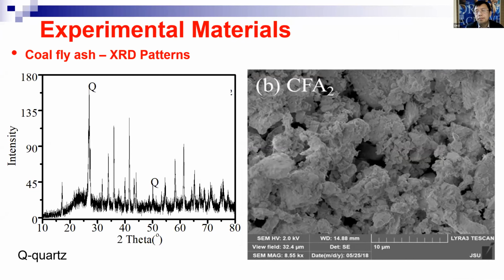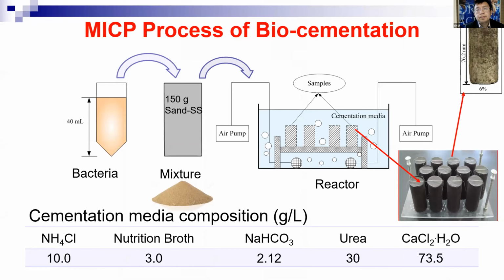The reason is, as we mentioned, this bacteria is about 2 micrometers long. So when the bacteria solution is mixed with fly ash, the bacteria need a little bit of space to go through, to mix well, or go through this coal ash. So there is enough void space in this coal ash for this testing. And now the procedure, how we do that.